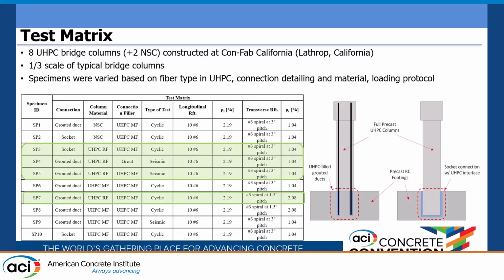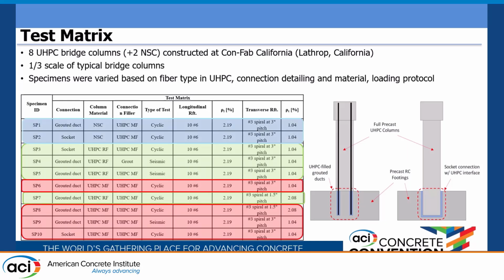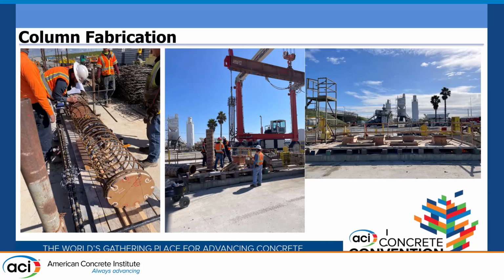I said earlier that we developed columns that have recycled fibers in them, 4 of them. These are identical to the ones with the manufactured fibers so that we can compare the performance. And also 2 columns are normal strength concrete, based on the Confab California cement, concrete I mean, that they use. So this is what we started. We developed the columns and assembled the reinforcement. We put a lot of strain gauges to see all the strains. At their precast bed, we formed the column formworks. And this is the final part, where we put the formworks around before the mixing.